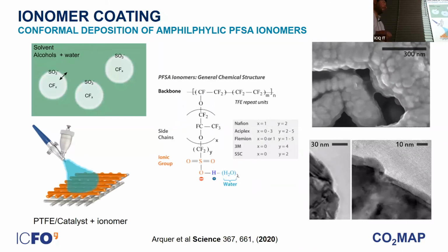So to achieve this increase in CO2 availability, we looked into a very well-known polymer in the field of electrochemistry, that's Nafion. Nafion pertains to a family of ionomers called perfluorinated sulfonic acid ionomers, which are characterized by having an ionic group of a sulfonic acid, which is hydrated and provides water transport and ion transport, and then a combination of hydrophobic backbone domains and side chain domains.